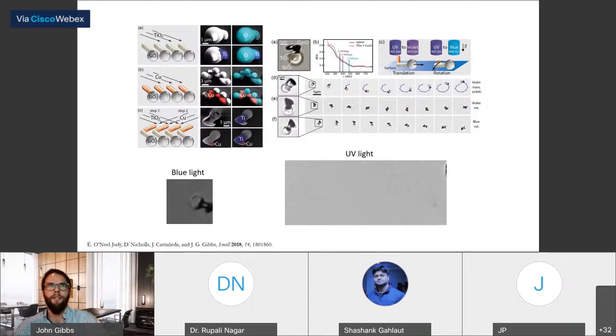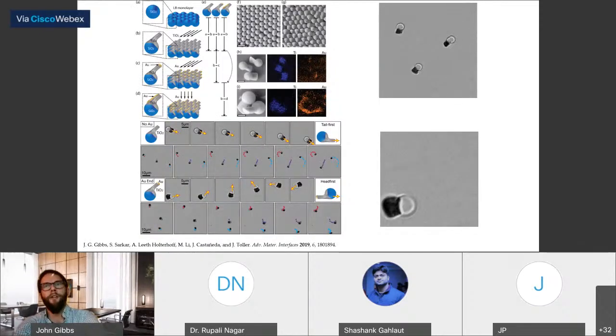So not just the fact that you have these two different band gaps for the two materials, but the interface between the two can actually have a strong effect on their interaction with light. Okay, so that's what this study was about here. And so instead of using two different semiconductors, we actually just used gold. And so as you know, if we have an interface between the TiO2 and a metal like gold, it actually changes the band gap also. And what we wanted to do is to take advantage of GLAD in order to put the gold on different segments of the TiO2 tail.